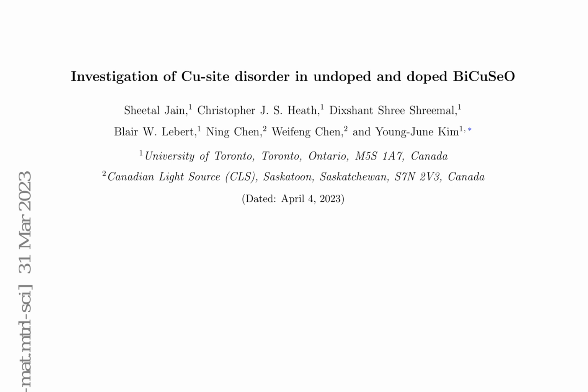Researchers investigated the origins of low lattice thermal conductivity in the thermoelectric material BiCuSeO and the effects of silver, Ag, doping on enhancing its efficiency. Through X-ray diffraction and extended X-ray absorption fine structure (EXAFS) studies, they discovered large thermal displacement parameters in copper, Cu, signifying disorder on the Cu site. These results reveal a scenario characterized by rattling motions within the BiCuSeO structure.